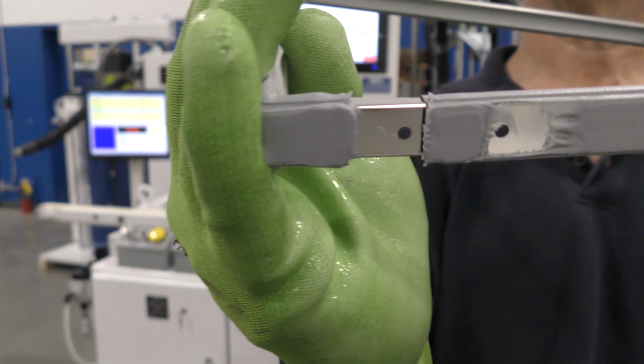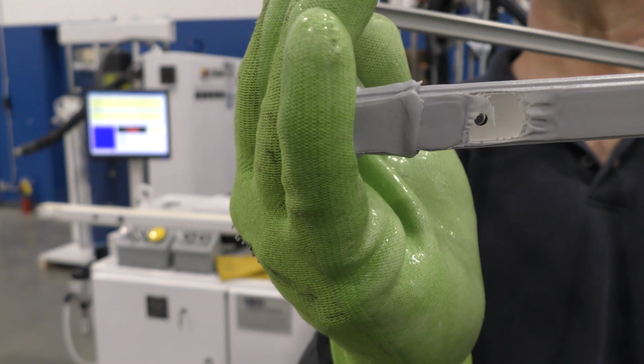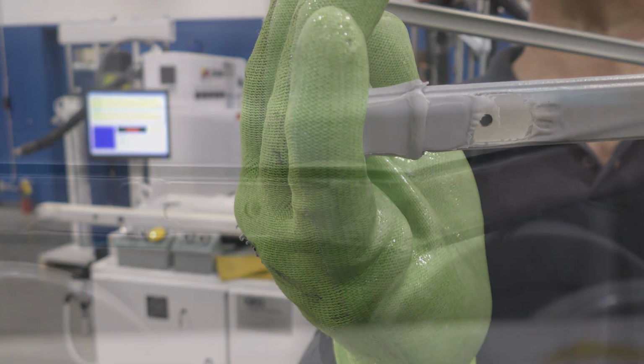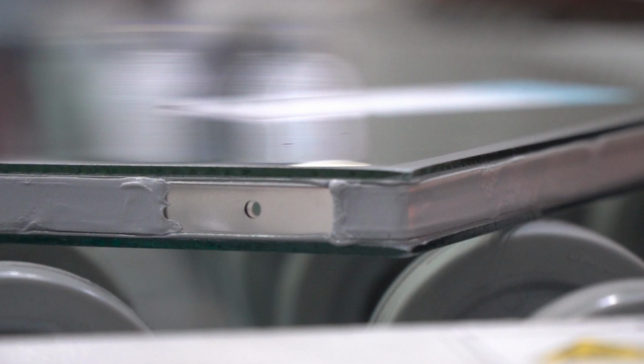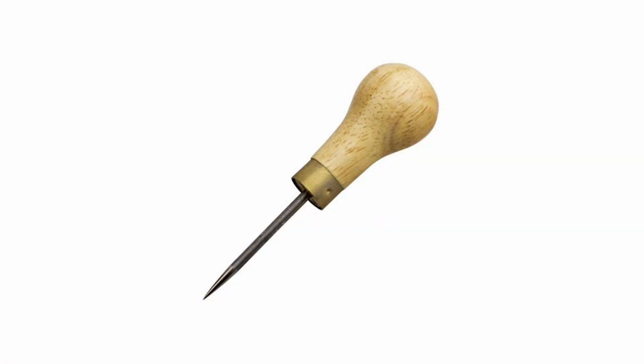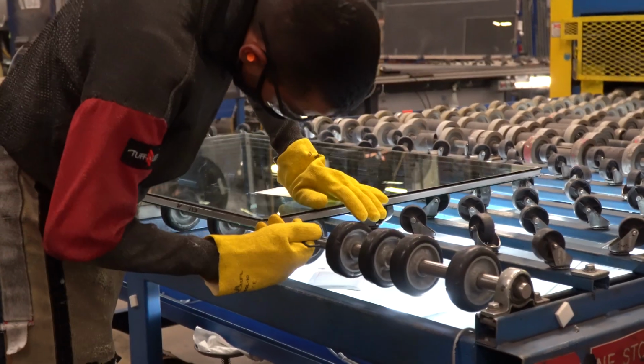The tab should be fully inserted so the holes are properly aligned. Misalignment of the spacer holes may be repaired by the worker removing the hot units from the oven. Using a pointed tool such as an awl, the worker can gently pull the holes into alignment while the material is still hot.